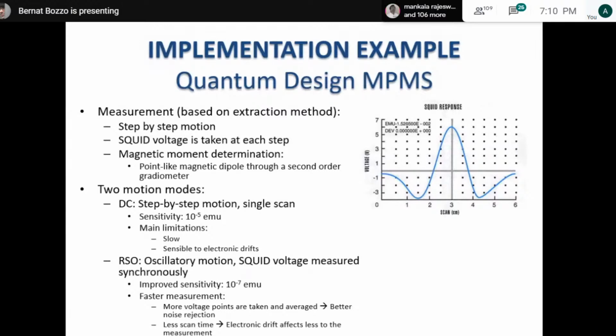Basically, this gives us a voltage versus position dependent curve like this one. If the sample is far away from the gradiometer, we get no signal. As we approach the bottom coil, our system will give us a voltage. As we move forward and approach the center coil, we have another peak, which is inverted in polarity and, ideally, twice the value of the first peak. As we move forward and approach the top coil, we get an identical signal as the first coil.